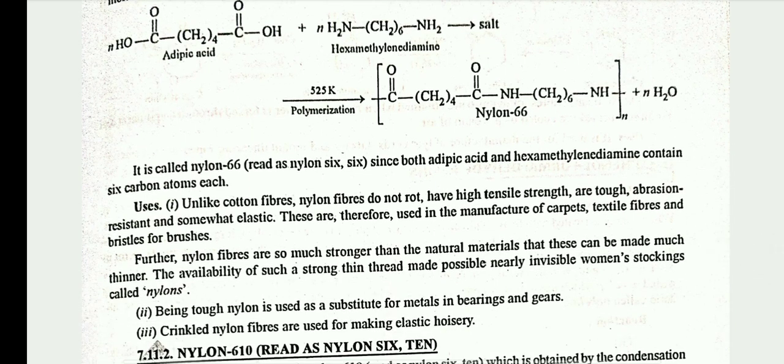It is called nylon 66 since both adipic acid and hexamethylenediamine contain 6 carbon atoms each. Uses: unlike cotton fibers, nylon fibers have high tensile strength, are tough, abrasion resistant, and somewhat elastic. These are therefore used in the manufacture of carpet, textile fiber, and bristles for brushes.